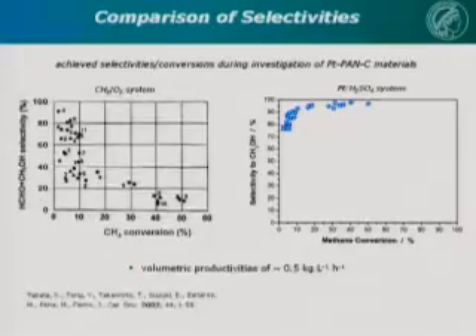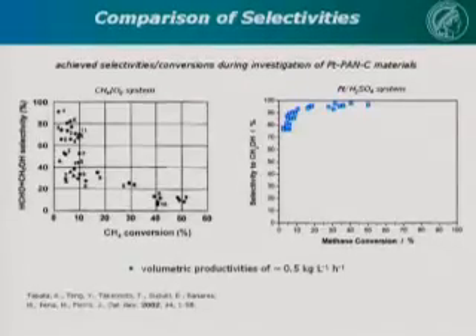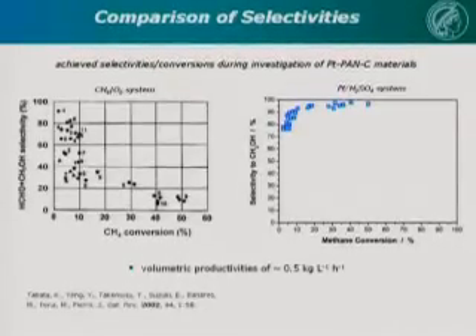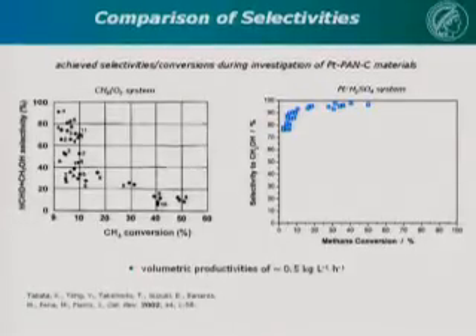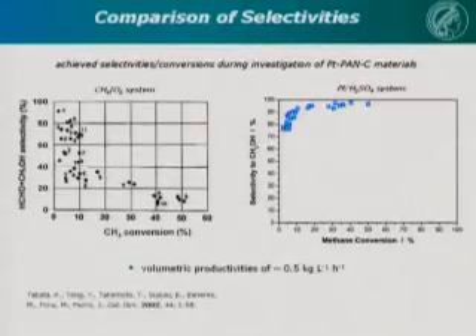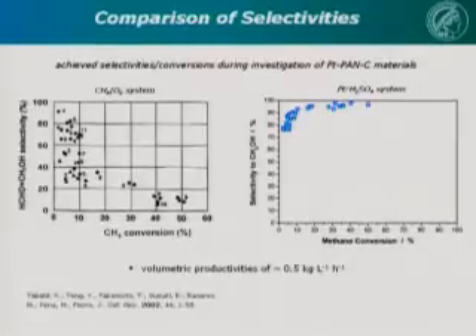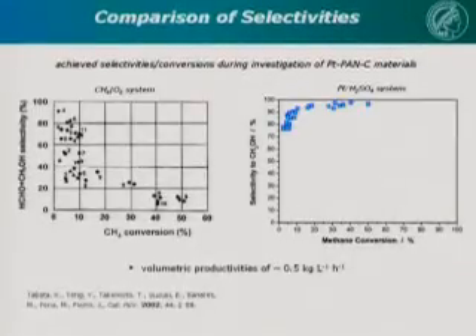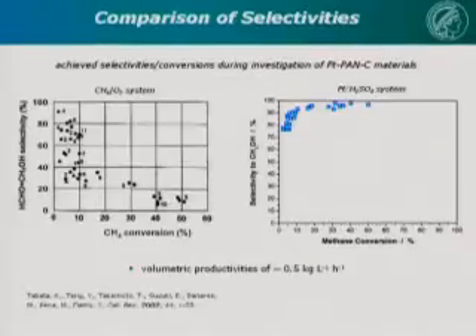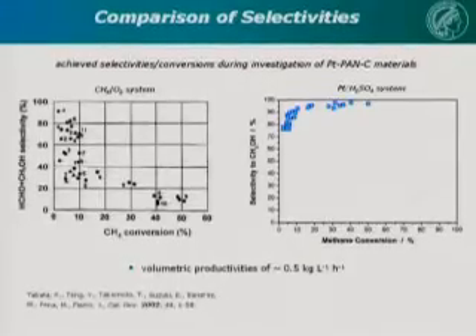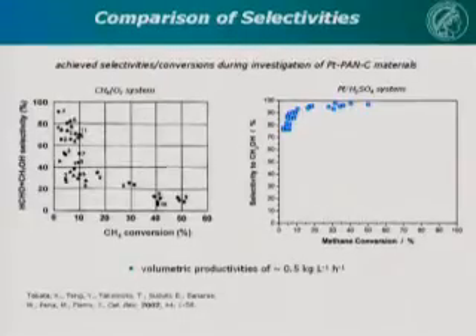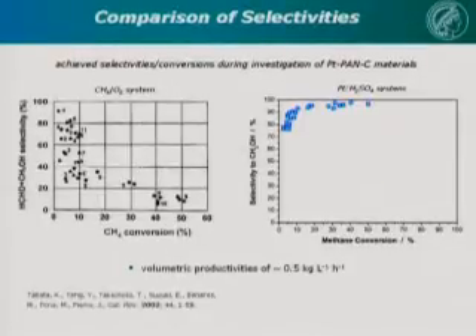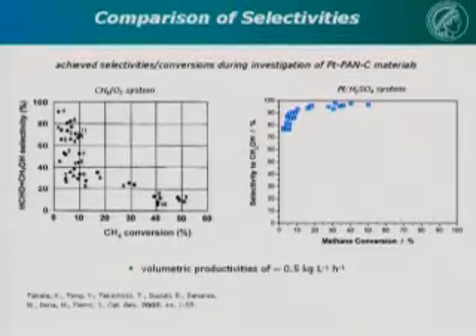And the very interesting thing for the Periana system is, while this here is the conversion versus selectivity curve for all other types of methane oxidation reactions, gas phase methane oxidations, high conversion, lousy selectivity, high selectivity, lousy conversion, this is totally different for the Periana system. Here we plotted many data points we had for our system, and what you see is your selectivity to methanol is, well, relatively high, almost 100%, and actually goes higher with higher conversion because we lose background reaction if we have sufficiently high activity. So this is indeed an interesting system.